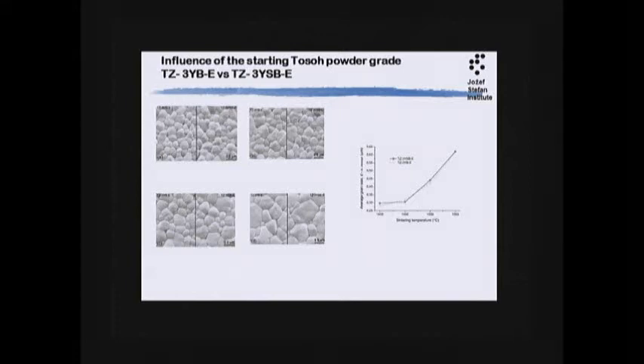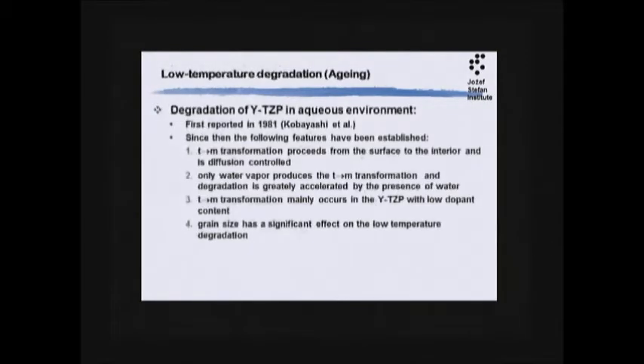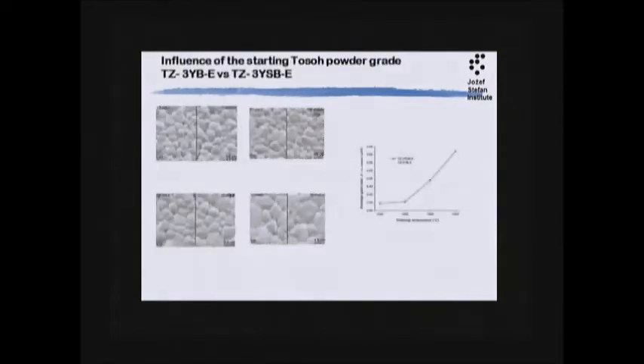Material, these two powders differ in the specific surface area, or calcination temperature if you want. Consequently, one material, the B, is a higher surface area material that will start sintering, densifying about 100 degrees C lower temperature than the other one.